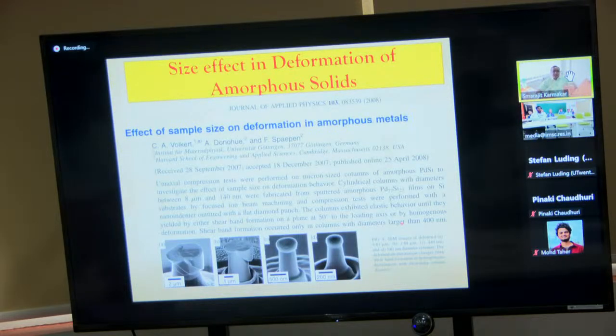So I will take 2 minutes and talk about the size effect, and then I can stop and take questions. Now I will show you some results when you go to nanoscales. It has been in the literature for quite some time that if you take nano pillars and deform them, and the pillar diameters are smaller than around 100 nanometers or so, you get deformation which is more homogeneous, like this bulging type phenomenon.